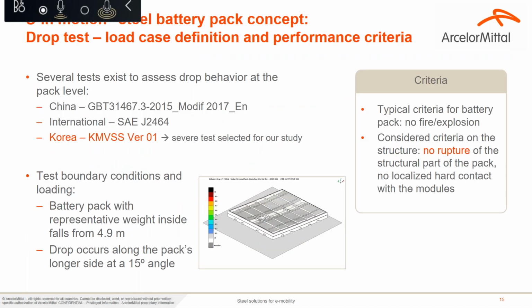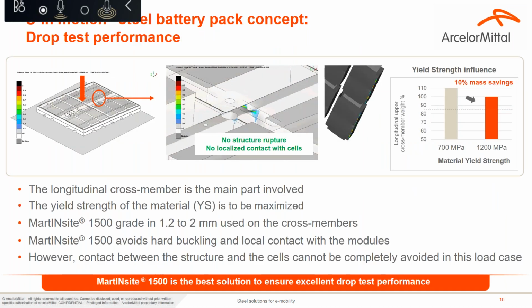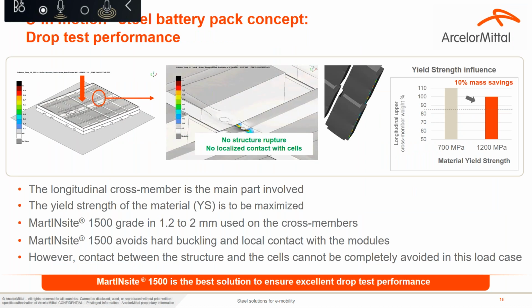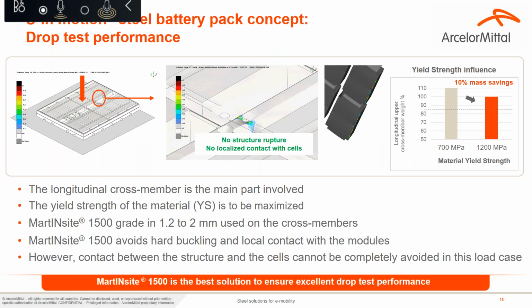Regarding drop tests that you can also find in different norms, we have selected the Korean norm, that is the most severe one. So you imagine a 430 kilogram module with the cells falling from about 5 meters high with an angle of 15 degrees. In this case, we don't want a rupture of the structure. And we found that the cross members were the most important.